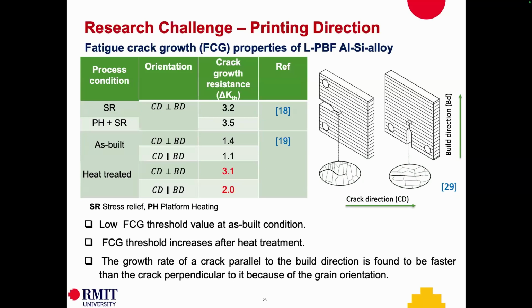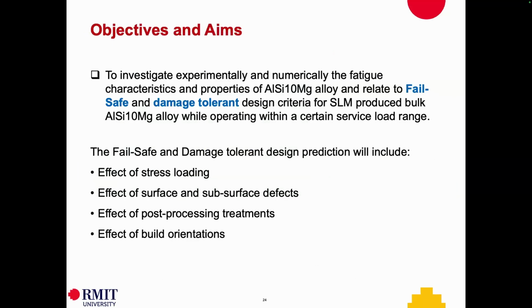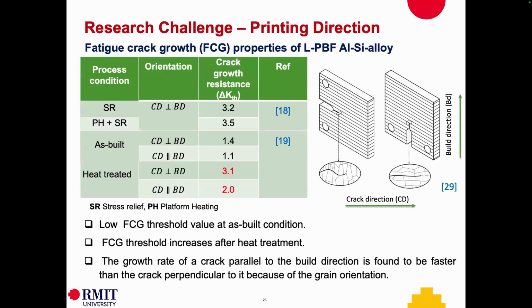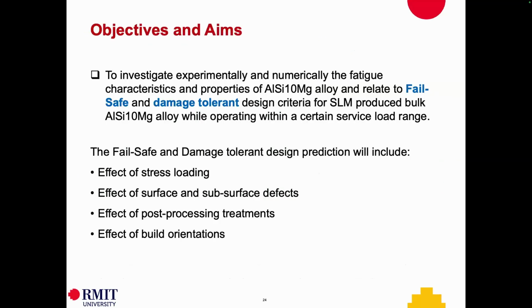It's not always true. A pore could be spherical or a pore could be different shapes, and that will control the fatigue life. Now let's look at what happens with the build direction. First, the printing direction is an issue. In general, what we found, if the printing direction is parallel, or 0 degree, with the crack growth direction, we get a lower life and lower fatigue threshold, as you see for all of those cases. But you can use heat treatment or other post-processing treatment to improve the fatigue life. So that's the challenge and how we overcome it, and we can control the printer.